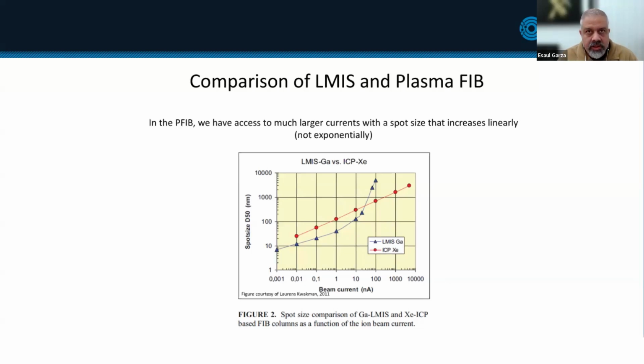And the other part is really understanding the materials that you're working with, meaning that you take the time to make sure you ground the sample correctly. If it needs sputter coating to mitigate charging, you do that. And also if you need to mark your ROI really well to minimize the time you're going to spend doing SEM, that also comes into play. And the last thing is really choosing the least amount of voltage and current throughout all these systems, meaning what is the minimum voltage and current you can use to be able to see the region of interest during the SEM, also during the FIB milling, and also during the imaging. You can also do low dose TEM imaging to prevent the total exposure.